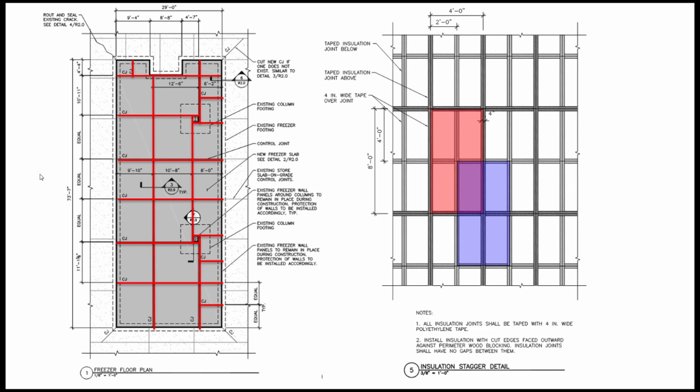The photo on the right shows the insulation layout for the boards we used, which was a total thickness of 8 inches, but we used 2 layers of 4-inch insulation boards that had the edges taped. We had a requirement that the boards tightly abut one another, and then we wanted them staggered. So basically we eliminated any possibility that you could have a joint line that concrete could flow down into, which would recreate the problem that caused the issue in the first place.